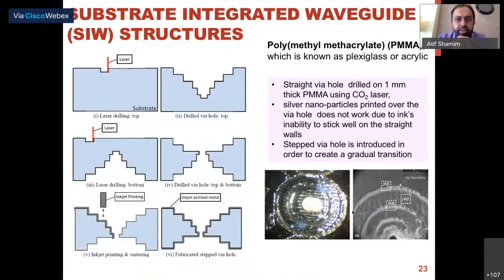a thick substrate, and then we drilled a hole through a laser, and then we tried to print in it, but that was not very successful because the ink would not stick to the vertical wall, and because the substrate was very thick, we would need a lot of layers to print to get one via. Was not practical. So we thought of a solution.